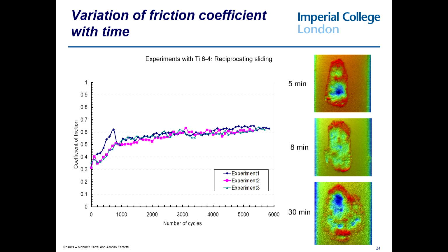So what you will see, these are scars, and the colors represent depth. The blue is a deep spot, and the red is high spots. You get material transferred from one surface to another, and the surfaces change quite considerably from how they were when you started the experiment. And this is going on all the time in our engineering systems, and yet we very rarely take account of it. The other thing is you might like to think that friction was at least constant.